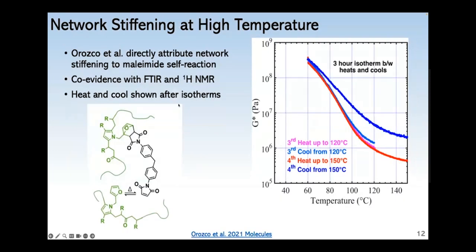In the next two slides, I'll share a few articles I found inspirational to my work. One of these was by Orozco and others, who also studied the maleimide self-reaction. They used FTIR and HNMR to confirm that the increasing disappearance of maleimide was in fact due to its self-reaction. But the way they also showed this was by taking a sample to high temperature, either 120 or 150 C, isothermal for 3 hours, and then cooling down. So I included one of their plots here.